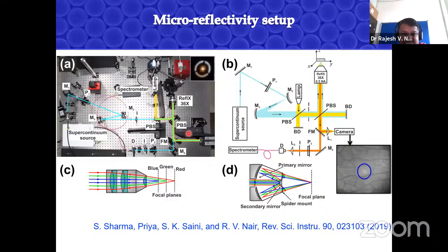I said I use this particular objective, the reflective objective, not the glass objective. The reason is that when we do white light spectroscopy, we need to avoid chromatic aberration as much as possible. From companies you can get a plan apochromatic objective, but that is corrected only for a few wavelengths, and we need a broad wavelength range. So that's why we use, instead of a glass objective, a specially made objective from Edmund Optics, called a reflective objective. Nowadays it's more commercially available, but at that time it was quite rare to get. So we could avoid this chromatic aberration. Otherwise, your result may be wrong. This itself is an instrumentation paper we published in RSI in 2019.